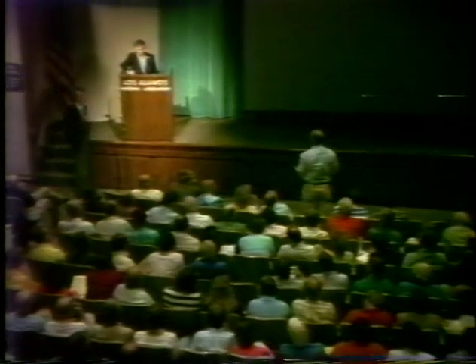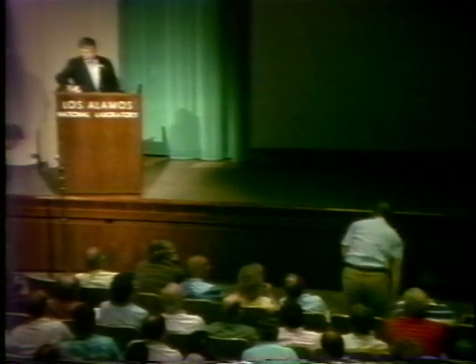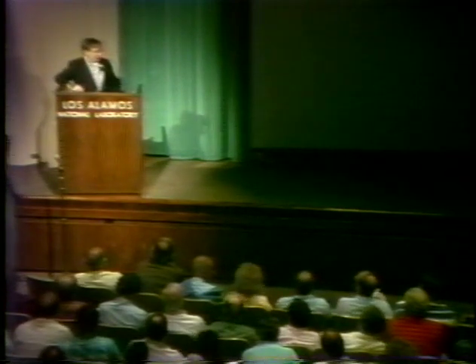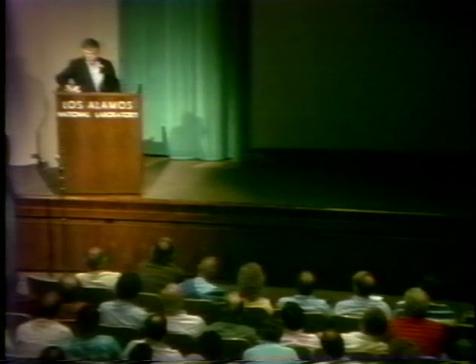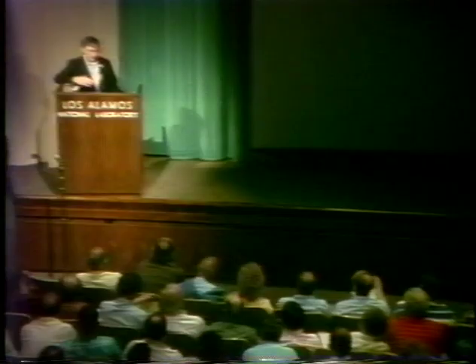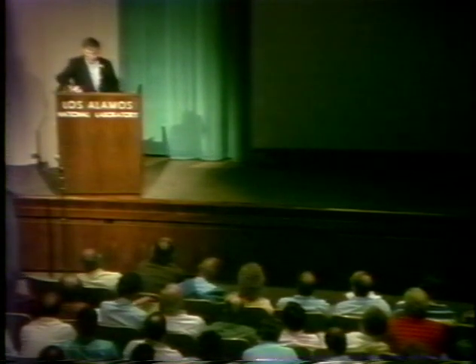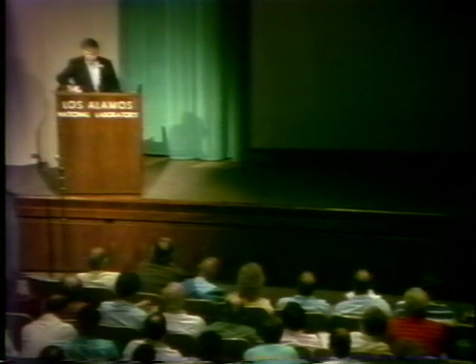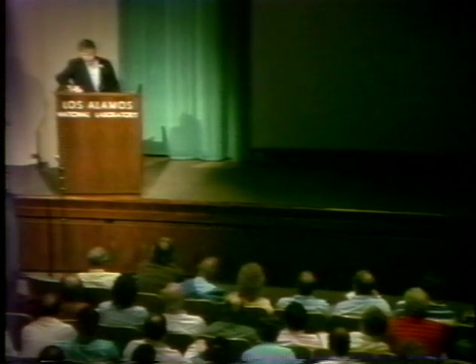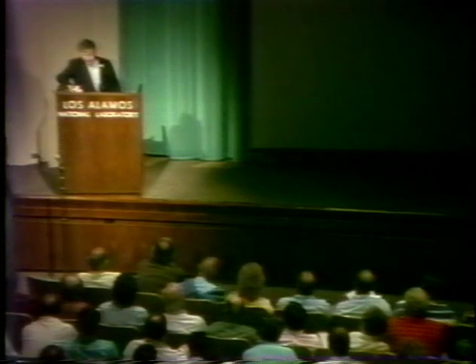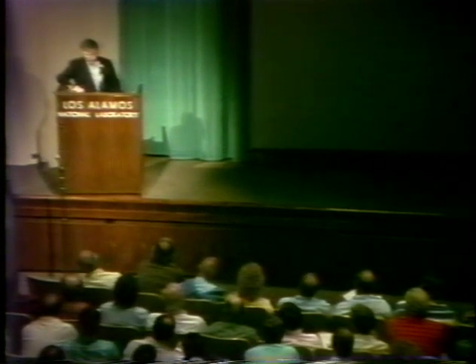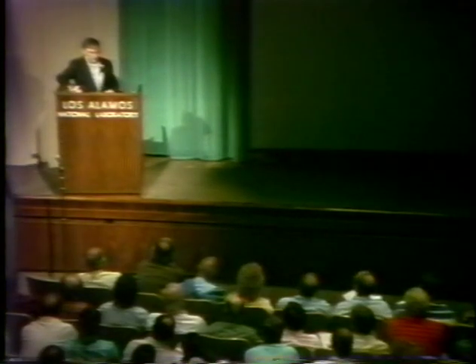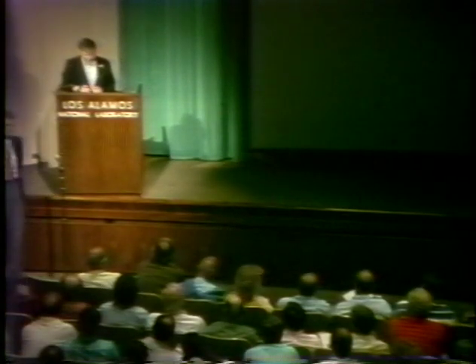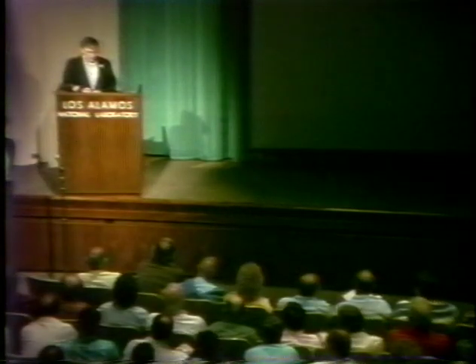Can you describe how long after the initiation of the experiment you first see excess heat, and then subsequently how long does it take the excess heat to reach equilibrium? All of the experiments, up to a 4 millimeter rod, are at equilibrium by 250 hours after we start. There is the expected rise in temperature that you would expect from just joule heating in the cell over about several hours after you start the experiment. And then for an electrode that takes, say, 3 weeks to charge up, you will see not too much of a change over the next week and a half, and then in the last week you will start to see the temperature rise up to the 6.5 degrees that you saw here. So that temperature cycle takes about a week. We usually wait about 5 times the diffusional relaxation time before we think the thing is at total equilibrium.